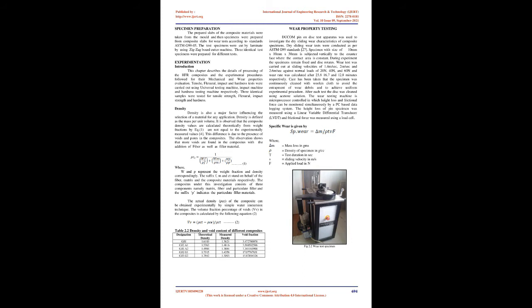Jute and glass fabrics were pre-impregnated with the matrix material consisting of epoxy resin and hardener in the ratio of 10:1. Care was taken to avoid formation of air bubbles during pouring. Pressure was then applied from the top and the mold was allowed to cure at room temperature for 72 hours. During the application of pressure, some polymer squeezes out from the mold. For this, care has already been taken during pouring. After 72 hours, the samples were taken out of the mold. After curing, the laminate was cut into the required size for erosion and other mechanical tests by a zigzag cutter machine.